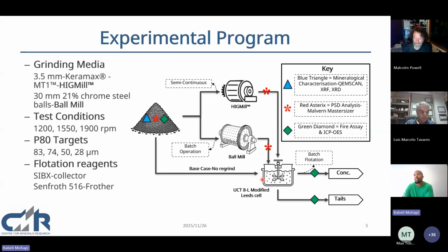We were not really concerned about the chromite entrainment or its effects in our concentrate, as most of the chromite was also recovered in the preceding recovery stages, as the Impala plant also has an adjacent chromite recovery plant next to it. For the analytical tools utilized, we did some mineralogical characterization of the feed using QEMSCAN backed by XRF and XRD, and we also did particle size distribution analysis of all the ground products and the feed, along with fire assay, which was coupled with ICP-OES on the flotation concentrates and tailings.